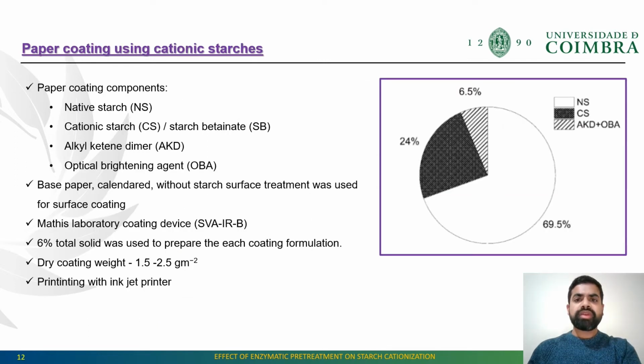Moving forward to the application part, these cationic starches were used to prepare the coating formulation, along with the general coating components such as alkyl ketene dimer and optical brightening agent. The native starch was used as a host component, and calendered base paper without any surface treatment was used for the coating operation. The laboratory coater was used to achieve 1.5 to 2.5 gram per meter square dry coating weight. Finally, all coated papers were printed using an inkjet printer. Further, the printing qualities were evaluated.